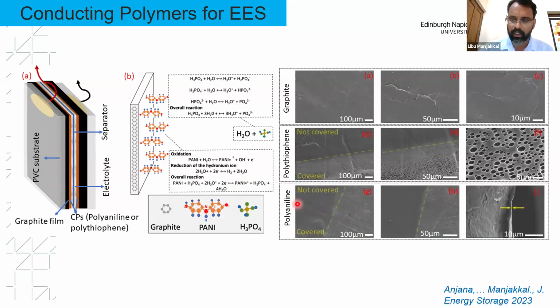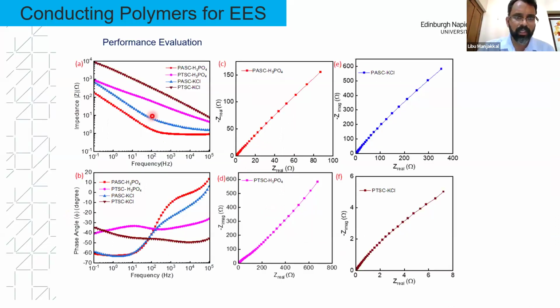or a capacitive sensor, a capacitive energy storage device. As you can see here, when we compared the polyaniline based supercapacitor and the polythiophene one with different types of electrolyte, we found that polyaniline with H3PO4 gave better performance, with a low impedance, which means it can store very high energy. You can see the impedance variation here, and then also the Bode impedance plot showing the variation of the performance.